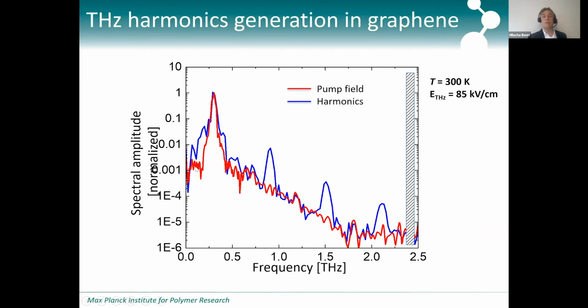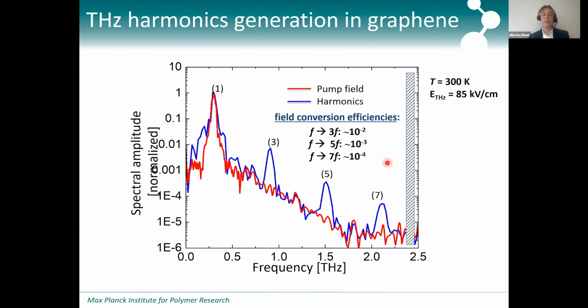So here you see again the fundamental, and superimposed on that you see the third, the fifth, and the seventh harmonic, which are well above the noise level of the experiment. So very efficient harmonic generation. And again, I'd like to stress this is room temperature, 300 Kelvin. It's modest field strength, 85 kilovolt per centimeter, and again a kind of 1% field conversion efficiency. So 1% for the third harmonic, 0.1% for the fifth, and another factor of 10 for the seventh harmonic.